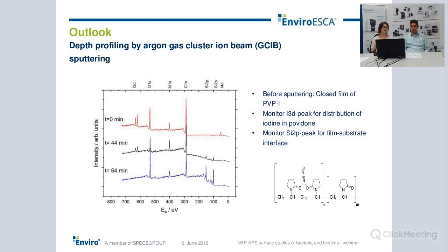Here you see survey spectra from 3 different sputter cycles: before sputtering, after 44 minutes of sputtering, and after 64 minutes of sputtering. Before sputtering, you have a closed film of povidone iodine.